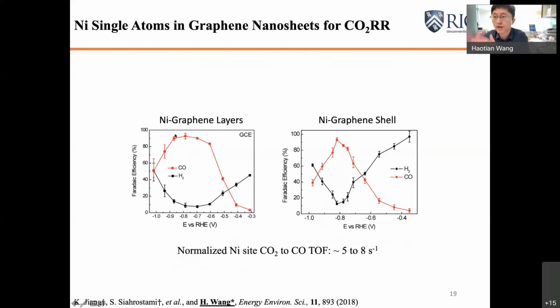As you can see, we have a much wider electrochemical window to get more than 95% selectivity. But if I normalize them back to the active sites, actually both of the catalysts, even though in different morphologies, share quite similar turnover frequencies, which means that even though their morphologies are different, their active sites are the same. Those are the nickel single atomic sites.